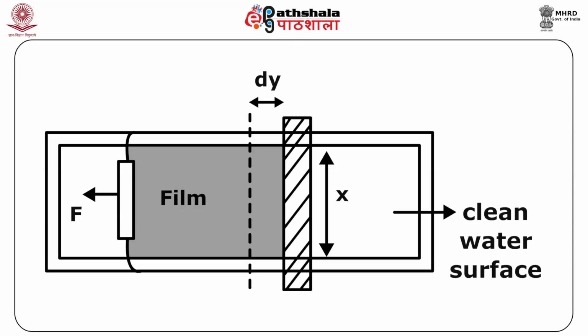When a drop of this dilute solution is added to water contained in a Langmuir tray, after some time the benzene evaporates and the stearic acid forms a thin film on the water surface. The film can be confined between a barrier and a float, against which any force can be measured with the help of a torsion wire. This has been shown in the figure. The area of the film can be changed by moving the barrier.